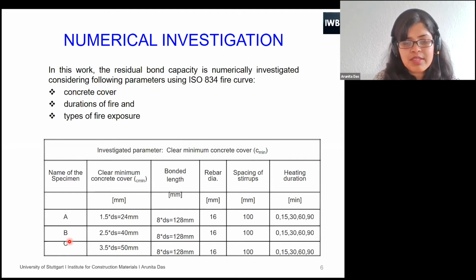For all the specimens, the diameter of the bar was 16 millimeter. Then the minimum concrete cover was 24 millimeter, that is 1.5 times the diameter, then 2.5 times and 3.5 times respectively. And I have considered a bonded length of 128 millimeter, and different heating durations. 0 indicates those specimens were not subjected to fire, those were basically in the residual state, then 15 minutes, 30 minutes, 60 minutes, and 90 minutes.